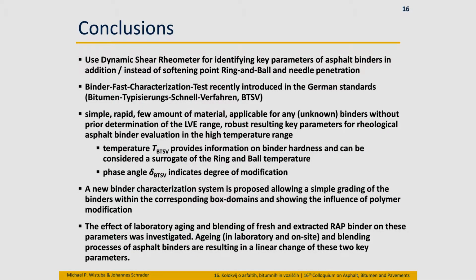We think that there is an increasing need to substitute the old traditional methods, softening point, ring and ball in the first step, especially when we do routine testing of asphalt binders, when we control quality. The binder fast characterization test using the DSR is a first step in that direction to determine binder properties in the high temperature range. This BTSV method is very simple. Even if you have never worked with DSR, I'm very sure that you are able to do it when we show it to you in 1 hour. It's very simple. You just need a DSR, but the test itself is really simple. It's rapid, 1 hour, and you have your test results.